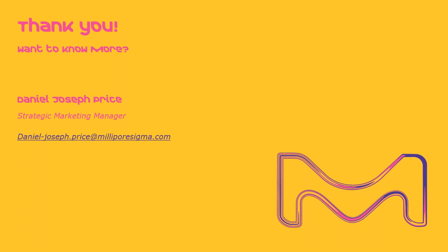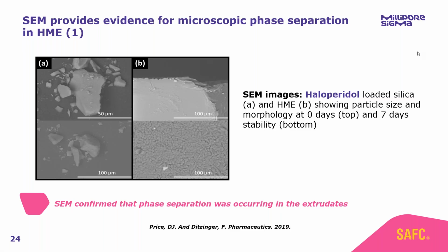Okay. Can you go to slide 24 or 25? The question is, what polymer was used for HME experiments? Yeah, absolutely. So I said we optimized the polymer. We used both computational approaches, solubility parameter predictions, and experimental small-scale screenings. We looked at approximately 10 different polymers, and the best polymer for both of these APIs was polyvinyl alcohol. That's what we used.